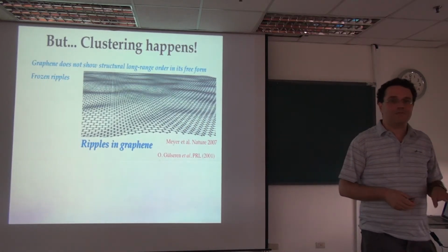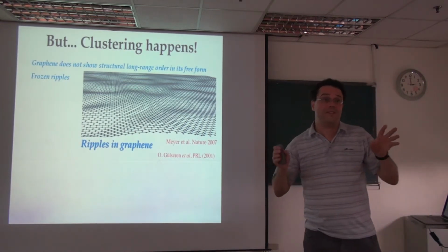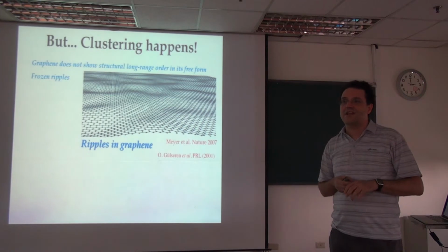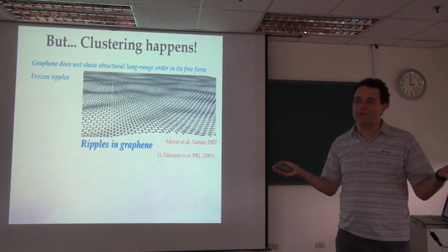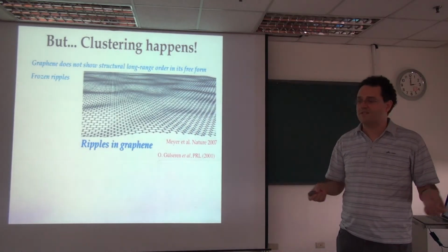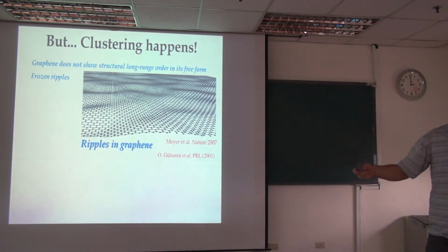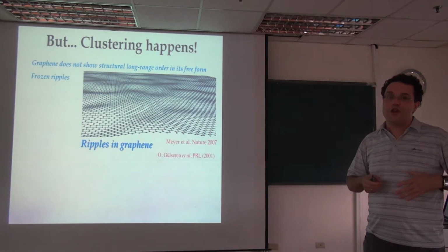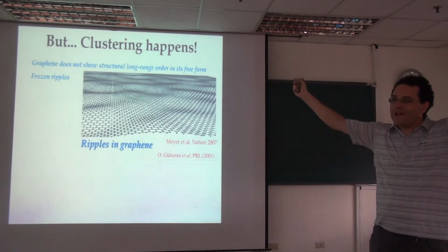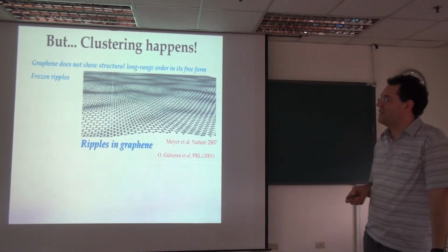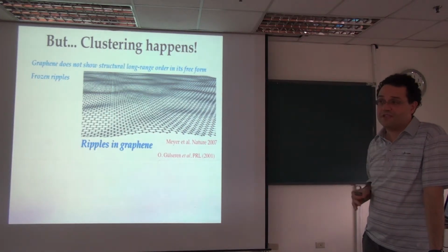This is perhaps, although it's not fully understood, related to the fact that there is a theorem in statistical mechanics, or also in high energy, that tells you that there is no long-range order in 2 dimensions. Right? And crystalline order is for example. Right? So the reason why graphene exists is because the samples are typically not infinitely large, not in the sort of what would be the thermodynamic limit, and the bonds in this graphene layer are very, very stiff.